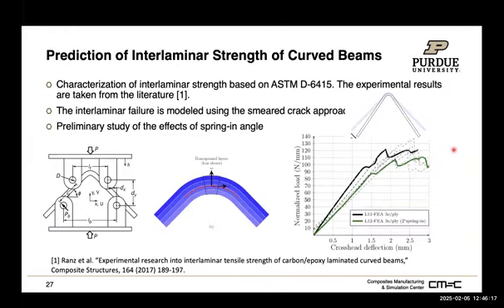This is one of the examples we've been demonstrating. Remember, we are actually fabricating those L shapes. We actually do the real manufacturing process now, so we do have those manufacturing coupons, and we can have a better understanding of everything that happened with this coupon. This is an ASTM standard experiment: a four-point bending of this L coupon. With the bending force applied, we do expect to see damage or failure, delamination, happen across the thickness of this composite panel.